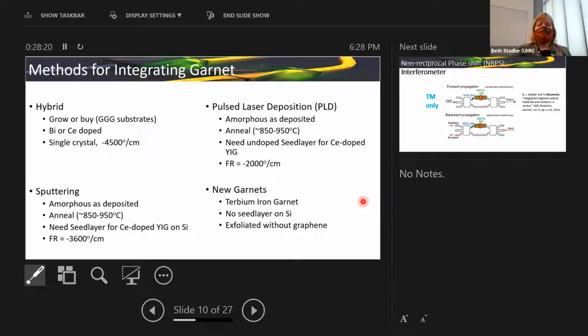We pretty regularly get like minus 3,200 degrees per centimeter out of cerium-doped terbium iron garnet. And the latest report that Carolyn's group had was they actually got like twice that in Faraday rotation. So I think the terbium iron garnet as a host instead of yttrium iron garnet is proving to be a good host.